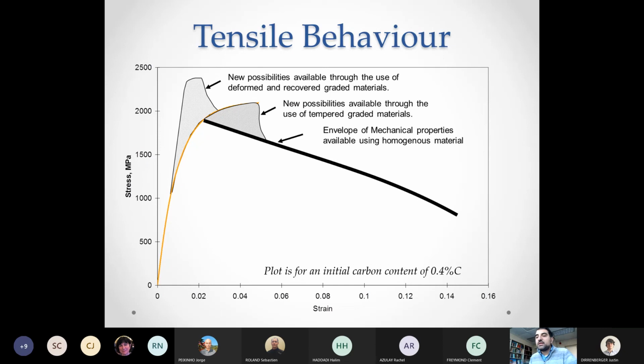I'll just summarize by showing some examples where the behavior of the graded material was better than the behavior of traditional materials. This shaded area here at the top is showing new combinations of mechanical properties that we could get by deforming the graded material. These are properties that we could not achieve with a uniform composition material. And then the shaded part here shows new combinations of properties that we could get by annealing or tempering the graded material. I put for comparison this dark black line, which shows what you can get by tempering homogeneous martensite. So you can see the shaded area here at the top. These are the properties that we can get only by using a graded material. We could not get that by using homogeneous material and tempering it.